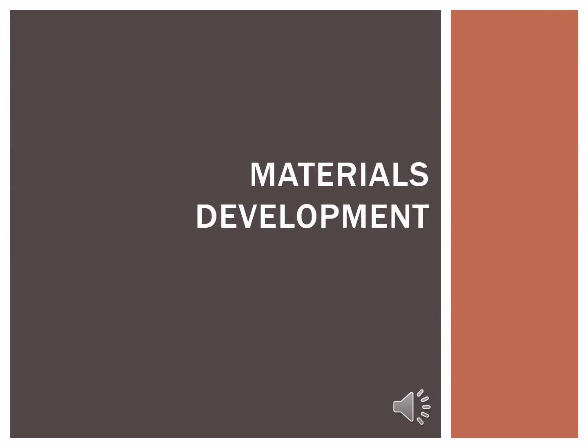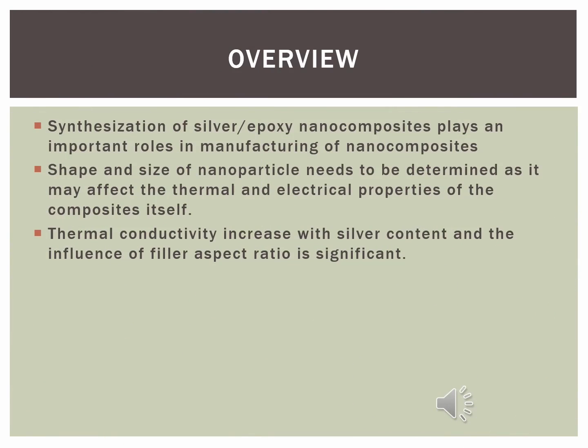Next is materials development. The synthesization of silver epoxy nanocomposites plays an important role in the manufacturing of nanocomposites. The shape and size of nanoparticles need to be determined as they may affect the thermal and electrical properties of that composite. Meanwhile, the optimum content of the filler is crucial in maintaining low density and high mechanical properties provided by the polymer matrix.